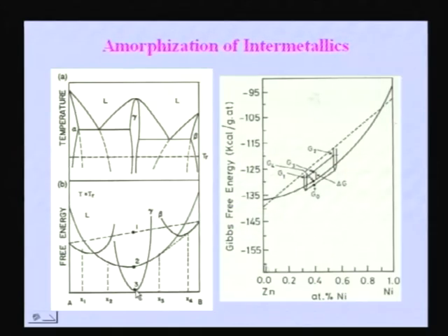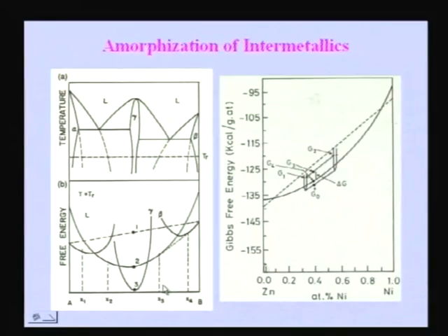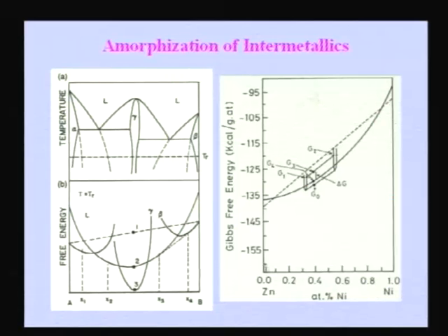What we do is, when we take such an intermetallic and start ball milling, you are putting so much energy into the system, and because of the defects that you are putting in, the free energy of the intermetallic goes up. You will come to a certain condition where the free energy of the intermetallic goes beyond that of the amorphous phase, and once that happens, suddenly there will be a driving force for the intermetallic with so many defects to transform into an amorphous phase. That is exactly what happens when an intermetallic tries to transform into an amorphous phase.